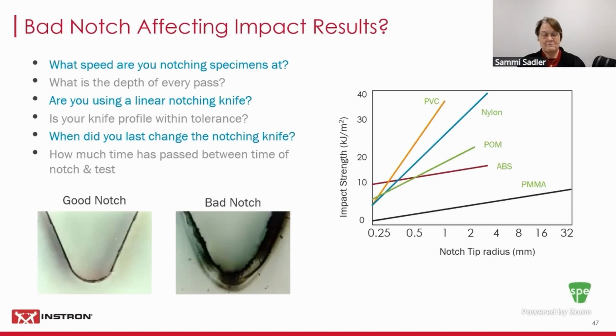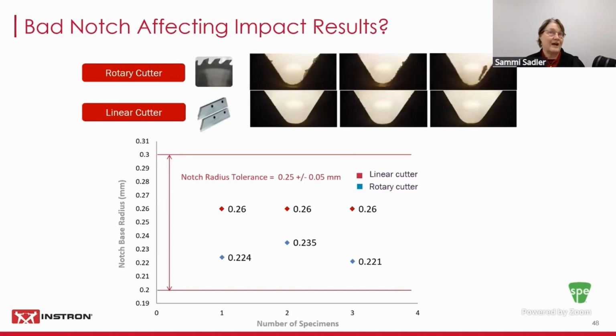So let's see. What do we do? So we did a little study where we used a single tooth or rotary cutter, and we used a linear cutter to see, well, what do the results look like? How repeatable could each of these be? And as you see with the linear cutter, if the notch radius tolerance was 0.25 plus or minus 0.05 millimeters, our linear cutter with the red is right on within that tolerance. However, the rotary cutter varied from being too low or too high. So we got much more consistent notches using a linear cutter than we did using the rotary cutter.